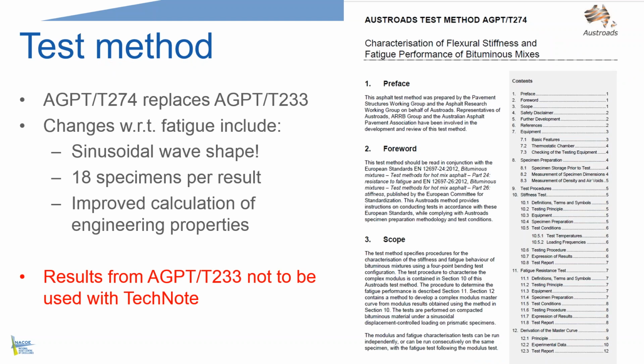And changes in terms of fatigue testing include that we'll now be testing with a sinusoidal wave shape instead of the Haversine, and the reason for that is that the Haversine wave shape that we used to use in T233 in effect resulted in a sinusoidal wave of half the intended amplitude, and therefore you would draw completely the wrong conclusions if you were interpreting that data. We'd be testing a minimum of 18 specimens per result, and if we're testing at a different temperature, we'll actually be testing slightly more. We'll be discussing that a bit later. And there are also improvements to general calculation and engineering properties that I don't have time to go into. But just for clarity, the results that you may have for mixes historically used from T233 cannot be used in this current tech note. You have to be testing in accordance with T274.